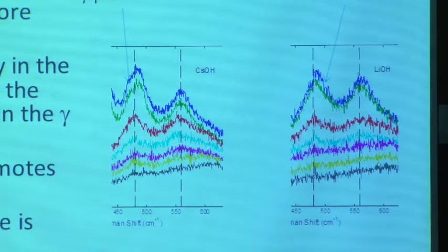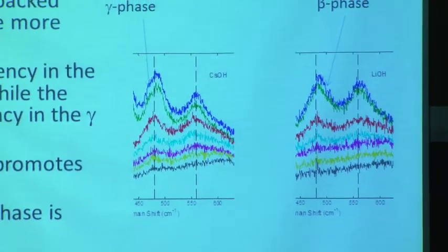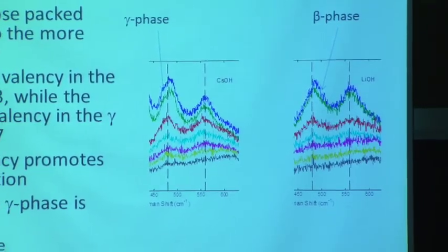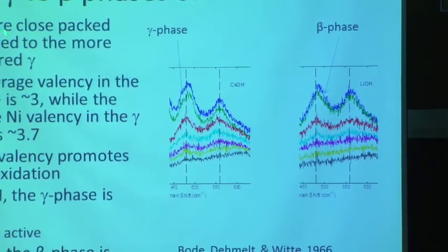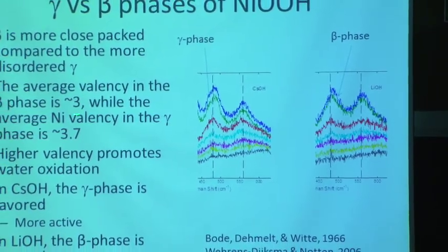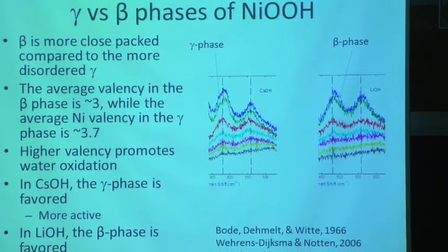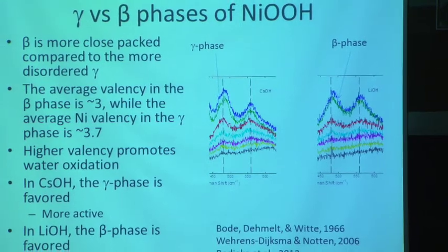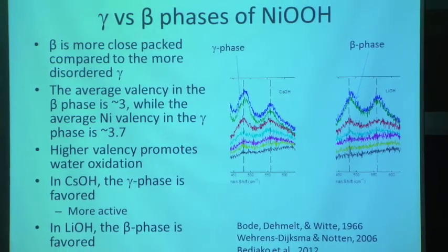So it's very difficult to distinguish beta from gamma. They're both nickel oxyhydroxide phase. The beta form is considered to be more close packed, and the average valency is about 3, while the gamma phase is considered to be more disordered and more open with an average valency of about 3.7. And so this higher oxidation state favors water oxidation. And so if you could promote the formation of gamma phase, you would be promoting this particular electrocatalyst.